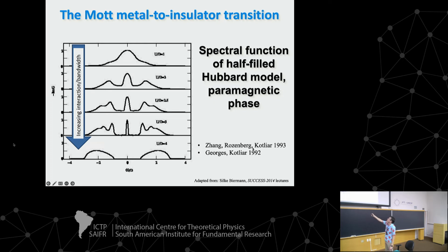So in the purely metallic limit, this is the density of states as a function of energy of the electron. In the purely metallic state, we have the band crossing the Fermi level, and as the interaction U increases, the width of this quasi-particle peak decreases, meaning that the effective mass will get bigger, and eventually the quasi-particle peak disappears, and you have the opening of a gap. All the spectral weight is transferred to the lower and upper Mott-Hubbard bands.